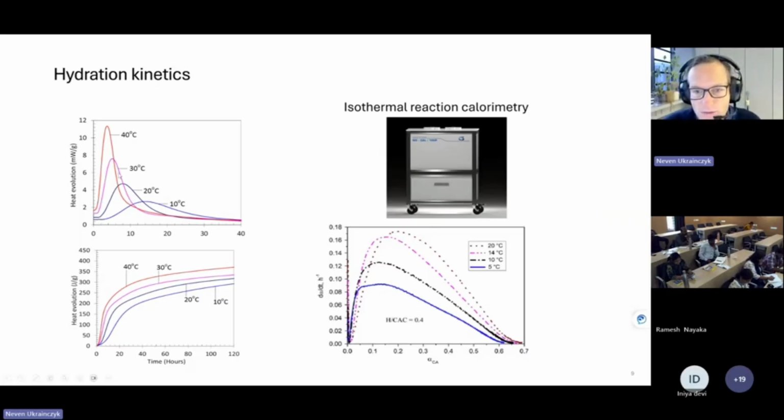So here they look shifted in a way, but because the time is not the real state parameter that defines it, the better parameter to get the master curve is the degree of reaction, and then you will get that all the curves are aligned. They are just multiplied by some factor, and this is exactly the activation energy.